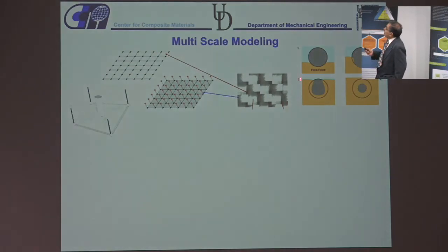So we decided to do multiscale modeling in our existing mesh, and again, we wanted to do it in a quick way. Remember, if I can give the industry 80% of the solution, they're happy, because right now they have 0% of the solution. So we said, okay, let's assign one-dimensional elements to our mesh, and these one-dimensional elements represent the fiber tows. These tows will have their own permeability, which will be different from the bulk permeability that you measure in the experiment. They will have a much lower permeability, and we can actually calculate the volume of the tows, so we can have a separate volume fraction for the tows.